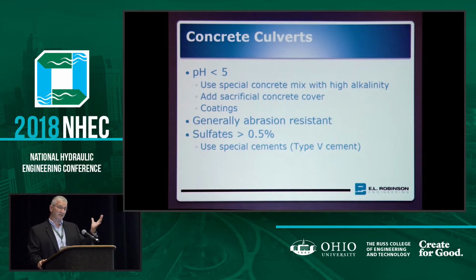Again, it's mechanically connected to the wall of the concrete, and so you do that. You have a really nice, long-lasting sacrificial layer, and you'll get tremendous wear out of your reinforced concrete pipe, even more than it already has, which is already really, really good. So, yeah. But it makes it really attractive in sanitary markets. So if you actually have a sanitary flow or something like that, I've seen PVC coated reinforced concrete pipe used in that type of an application pretty frequently.